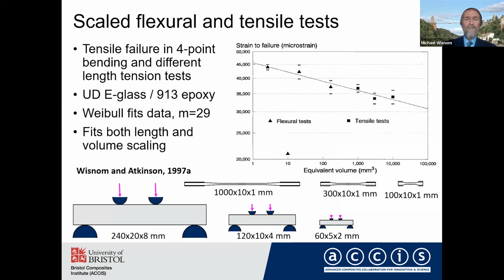We also did tests a long time ago on scaled flexural tests. These are glass epoxy specimens, where again, we changed all the dimensions, length, width, and thickness. And we also, with the same material, did some tests where we just changed the length. And you can see in this plot here, again, we plotted this as a Weibull plot, and you can see that the data fits on this straight line.